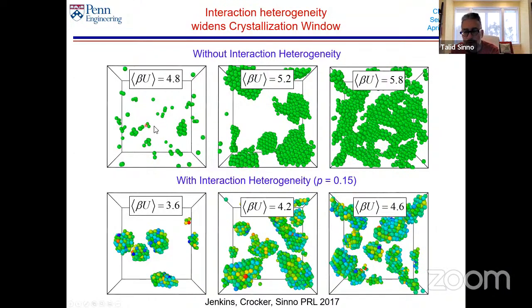So there's a pretty narrow window of going from nothing to gel. And there's only a tiny window in which I form nice big crystallites. So this is the standard case where every particle is the same. Now, when I go to an interaction heterogeneity of 15%, the colors on the particles represent whether they're strong or weak binders. Red is a strong binder, blue is a weak binder, and green is an average binder. And now, in this case, instead of 4.8 to 5.8, I go from 3.6 to 4.6. What you see is that you maintain crystallinity in the system over the entire window of this one kT of interaction strength.